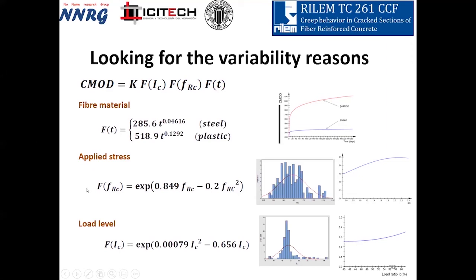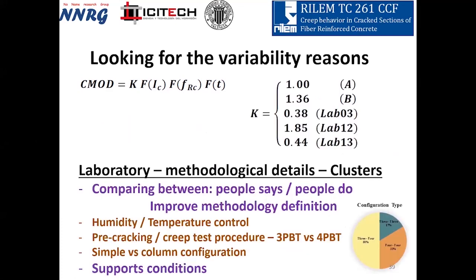The load applied and the intensity of load applied are also important, but as we always work with a relatively constant value, these values are not too influential in the final results. What we also detect is the effect of the type of laboratory working. We were able to classify laboratories in clusters. Cluster A has 7 laboratories, cluster B only 2 laboratories, and 3 individual laboratories clearly produced a methodology that is clearly different. This is thinking only of the flexural test.